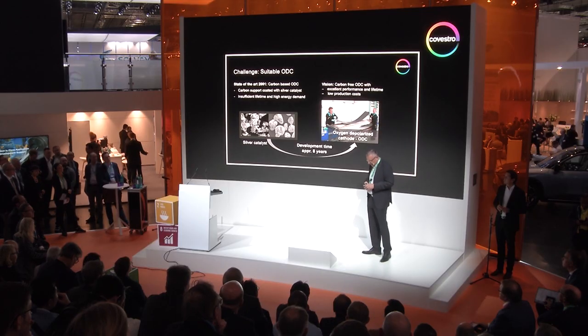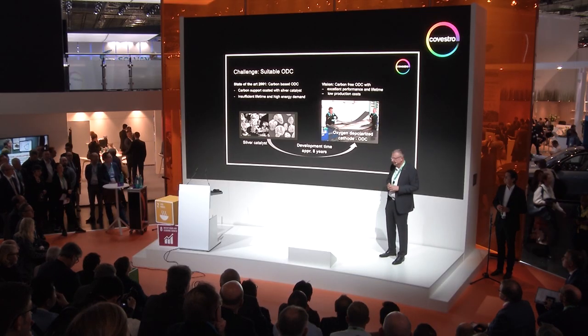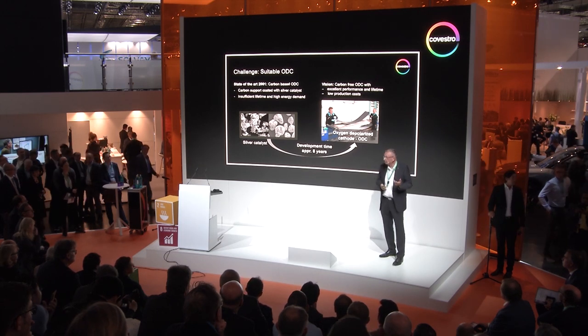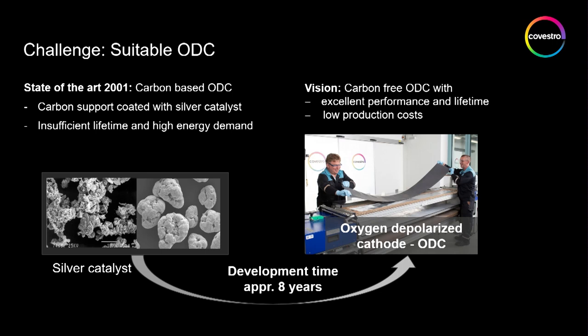When we started the development of the ODC nearly 20 years ago, we took the common technology. It was a silver catalyst supported on carbon material. And we learned during the first months of operation that this kind of electrode wouldn't be stable, because they are consuming not only oxygen, they are also consuming the carbon they consist of. So they were destroyed. The lifetime was insufficient, 3 to 4 months, and we need lifetimes of up to 8 years. So the idea was that we want to have a carbon-free ODC. This was done by taking a special kind of silver catalyst, and it took 8 years to develop such an electrode.